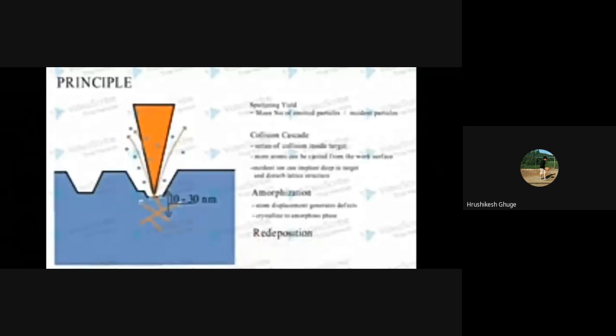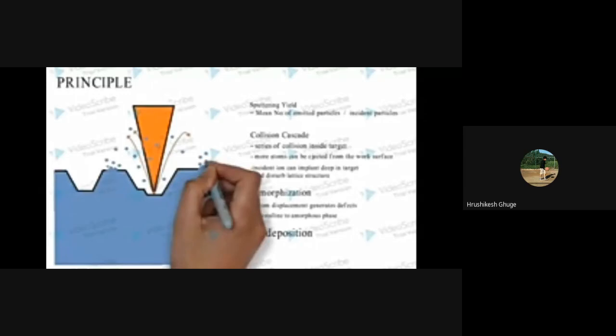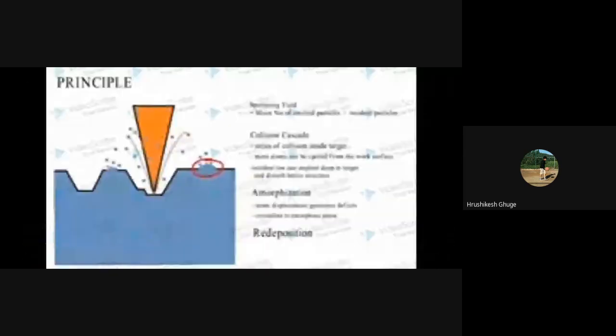There is another phenomenon observed in the ion machining process, that is redeposition. As this whole process is occurring in a vacuum, the atoms removed by the sputtering process sometimes cannot be evacuated by the vacuum system. They can get deposited on the adjacent surface where the milling is going on. The redeposited material sometimes settles on the side and other surfaces. That will lead to sputtering a second time, which obviously increases your process time and effort. So redeposition is surely an undesirable phenomenon in focused ion beam machining. Redeposition is observed highly when there are holes or fringes or narrow slots, where the redeposited material is also difficult to evacuate.